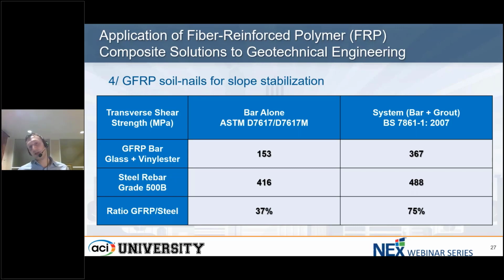So what this table is telling us is a non-metallic system behaving in shear can develop actually way more than we suspected, actually a lot, 75% of what the steel system performs. And even more interestingly, the value of 350 MPa is actually what you get from von Mises ratio. So actually, in this case, the GFRP bar develops more than what you would assume for a steel system. So it would actually offer you all the safety you would expect in your design.